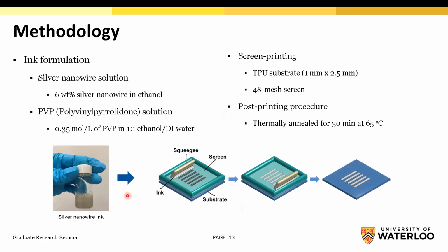Methodology: here we can see the ink formulation. We used a silver nanowire solution and a PVP solution, and by mixing them we get our silver nanowire ink. We screen printed our silver nanowire ink on a TPU substrate with a 48 mesh screen, and then we sintered at 65 degrees for 30 minutes.